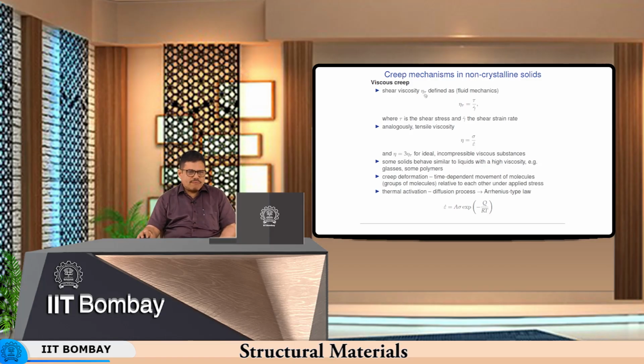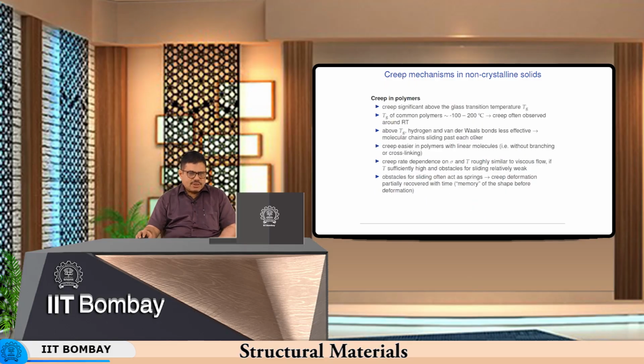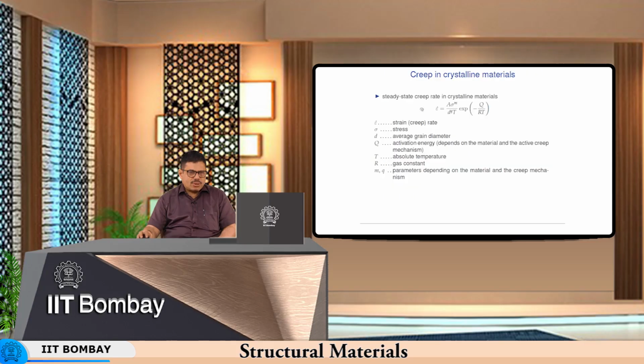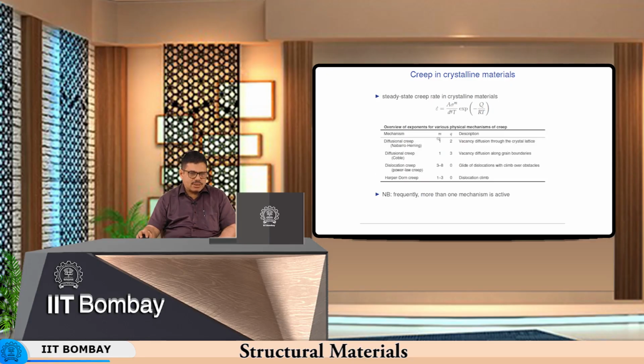So, we have different viscosities in creep, and we have seen that the thermal activation of the diffusion process follows the Arrhenius type law, and so strain rate is equal to A sigma to the power M exponential minus Q by RT, where Q stands for activation energy for diffusion. We have seen creep mechanisms in polymers and also steady state creep in crystalline materials, and we have seen that there are different mechanisms resulting in different values of these exponents of M and Q.